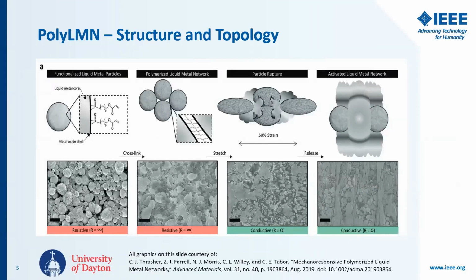These polymerized metal networks work very well for this specific application because of their structure and makeup. They are composed of a eutectic blend of gallium and indium, which has a melting point below ambient room temperature, and is separated into nanoparticles by means of a probe sonicator. These nanoparticles are then functionalized by means of a ligand shell and suspended in a carrier fluid, which allows them to be patterned onto various substrates. We particularly use thermoplastic polyurethane, or TPU, in our lab.